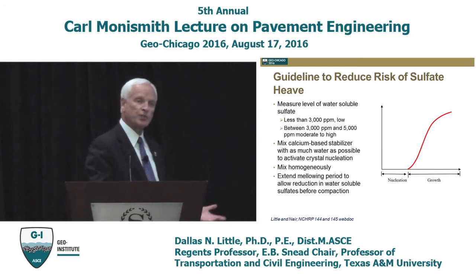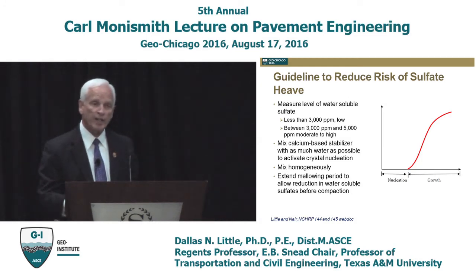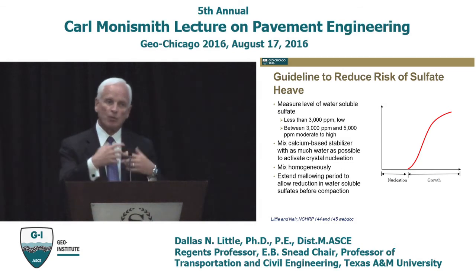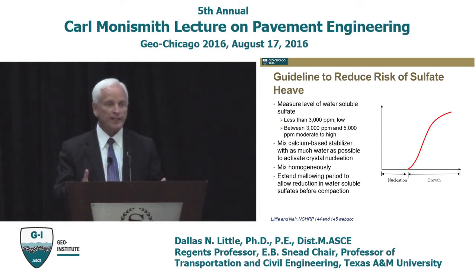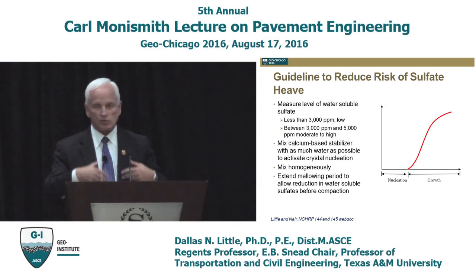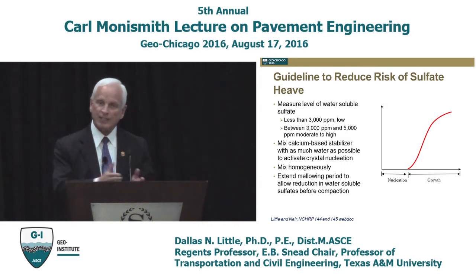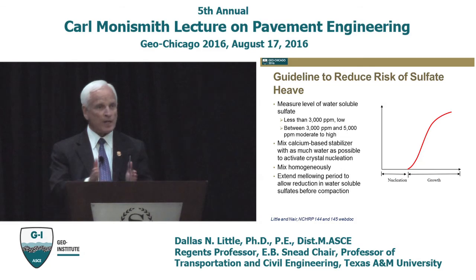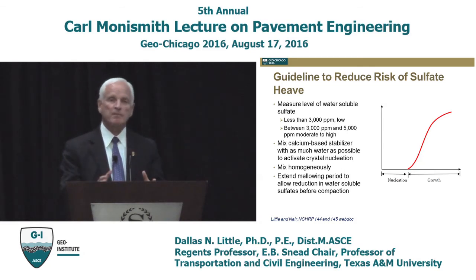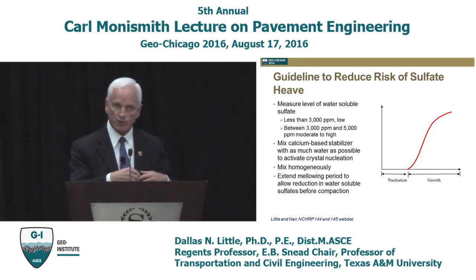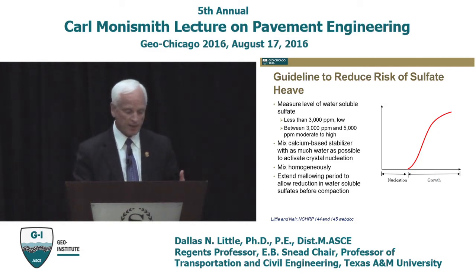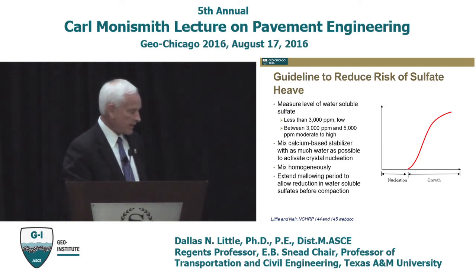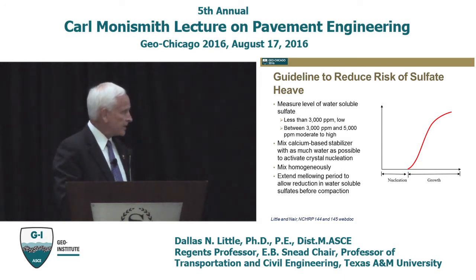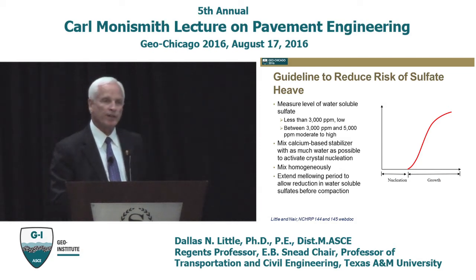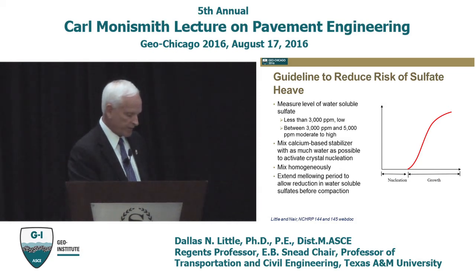So how do you maximize the rate of the crystal growth? Well, one way is to make sure that you continue to keep it wet, to keep it mobile, to keep it fluid. You mix it as much as you can to get a good intimate mixing, and you extend the mellowing period. Why do you want to extend the mellowing period? To give it time for as much of this crystal growth to occur before you compact it as possible, and also to make sure that you have used up as many of the constituents as possible.